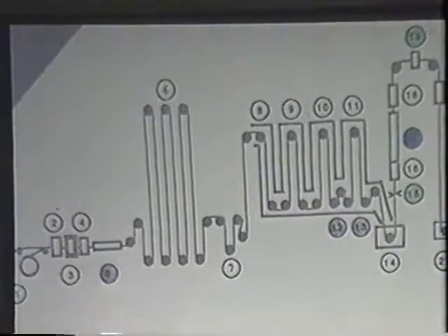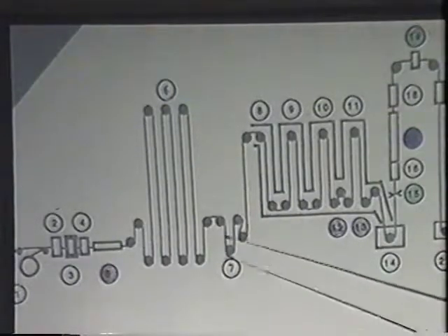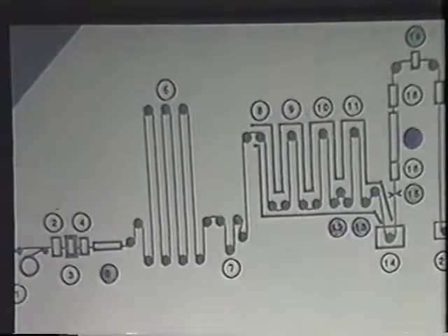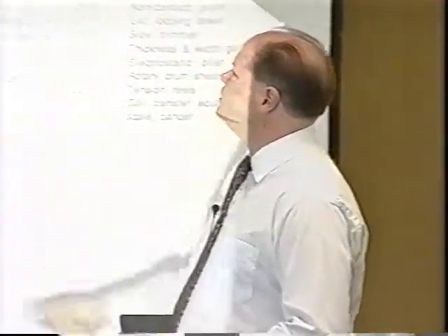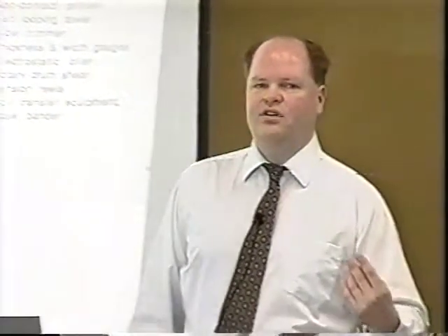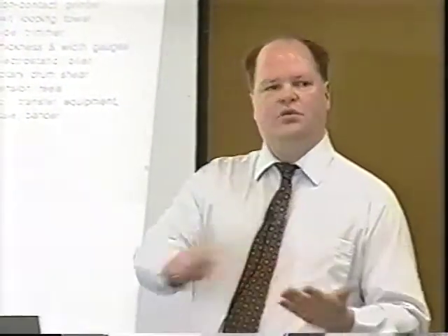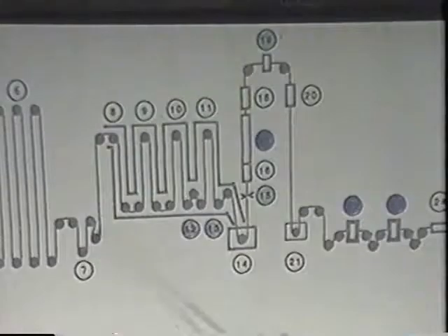It goes through a little bit of a pre-cleaner, which knocks off some of the tandem mill oils and fines. Goes through the entry tower. Comes up to our cleaning section. We have what we think is a very good cleaning section, probably one of the better ones around. It has electromagnetic scrubbers and magnets and good cleaning solution in order to get a good clean strip. In hot dip galvanized, or actually in electro galvanized, anytime you want to put something on the steel, you've got to have it very clean. So we have a very good cleaning system, with scrubber brushes, magnetic separators, things like that, in order to get a clean surface. You want it clean before you anneal it, so you get a good anneal, and then you want it clean when you coat it so the zinc can stick to it. So there are two reasons to get a good clean strip.